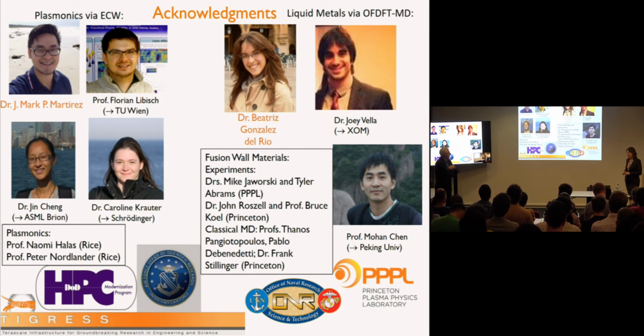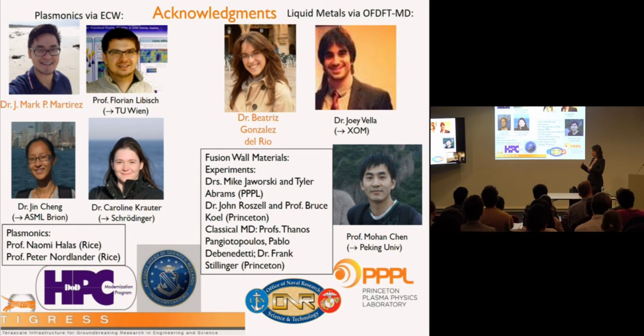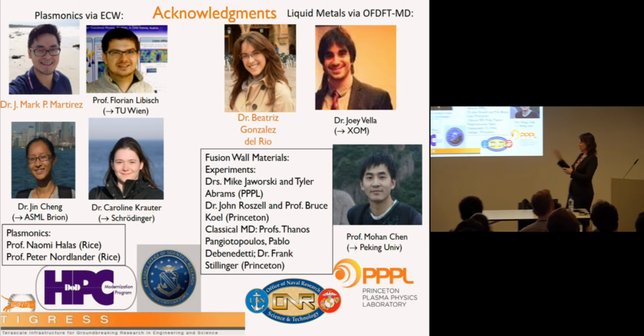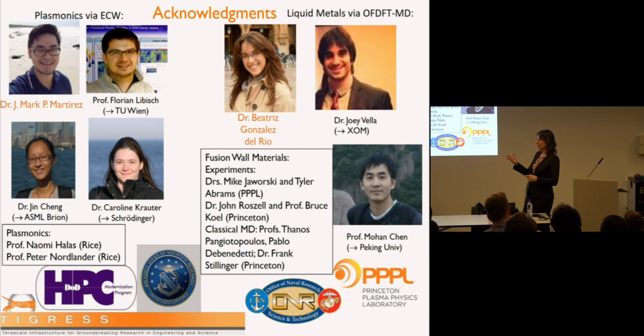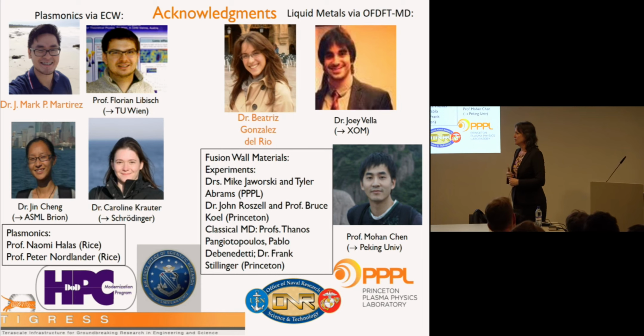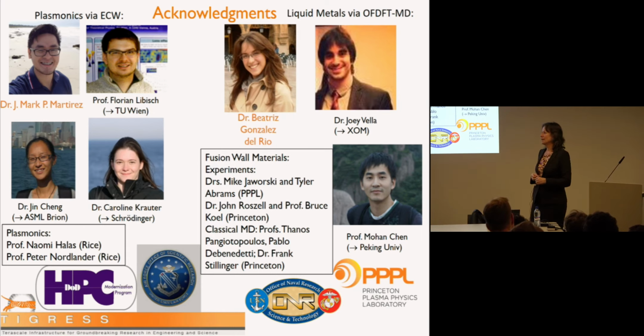We have done tests deliberately on finite systems, small enough that we can do the full correlated wave function calculation. So that's where we can do the tests. And then with respect to the other work that we've done, for example on metals, we increase the cluster as much as we can to see that the results are converged, and we live with that. And then we do our best to compare with experiment, especially for ground states. We've done quite a bit of benchmarking with respect to that.